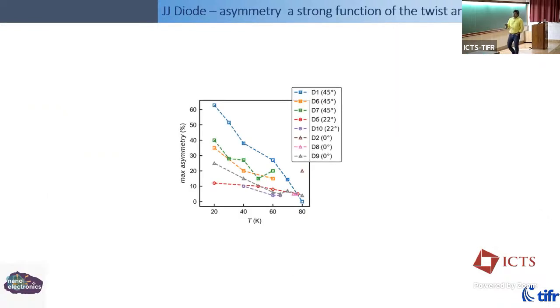Okay, so largely the asymmetry is largest for 45 degrees, and for controls that we did, the asymmetry reduces as a function of temperature, but is the largest for 45 degrees and very small for other angles.